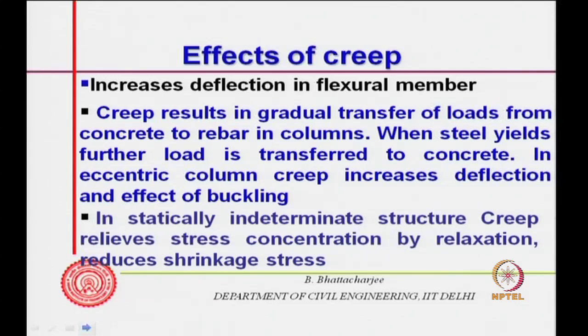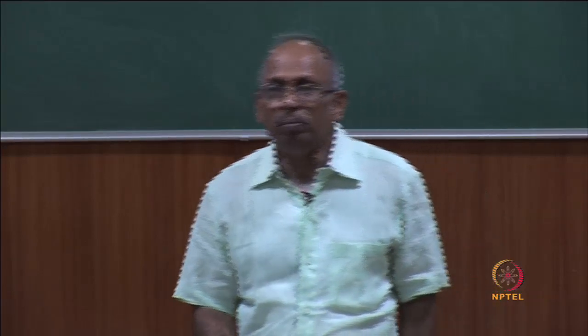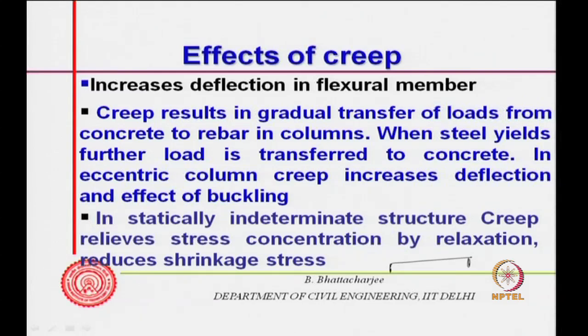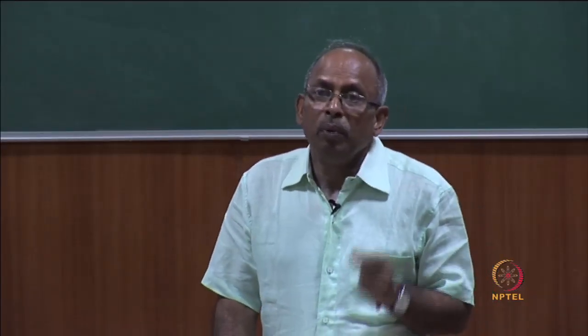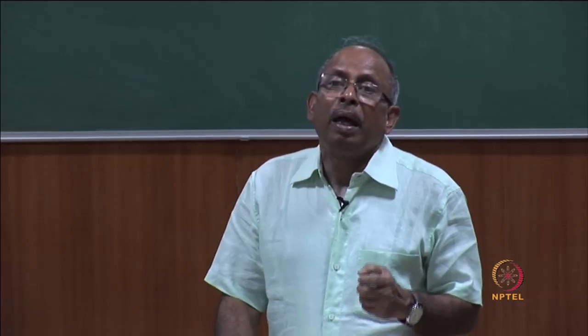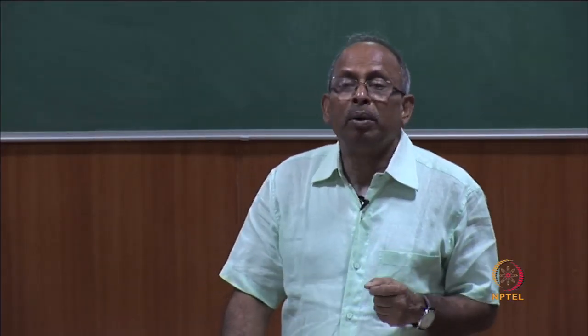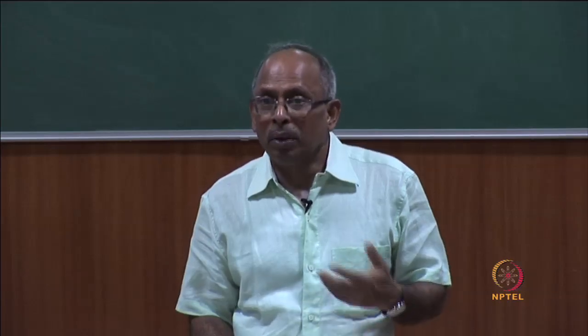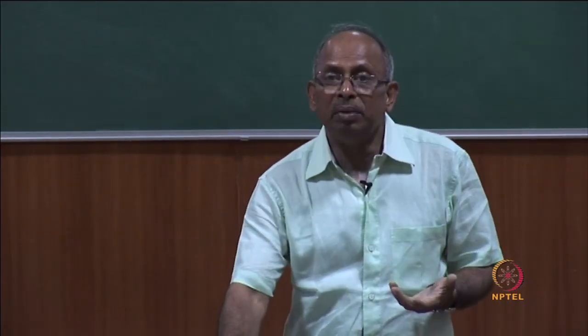In statically indeterminate structures, creep relieves stress concentration by relaxation and reduces shrinkage stress. Now, what is an indeterminate structure? You have additional restraints. For example, in a determinate structure, you will possibly have a roller and a hinge here, so this can move, but if you make another hinge, so two hinges here, it becomes indeterminate, so therefore it is restrained. So statically indeterminate structures are restrained. Now we have seen that when you put in restraint, some amount of relaxation will occur. So therefore, the stress in the concrete will reduce down. So it causes some relief in the stress, right.